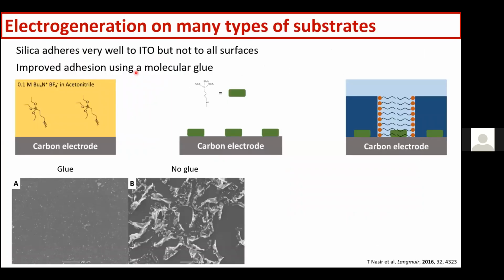So we can electrogenerate these on many conductive and semiconducting substrates. It works very well on ITO, indium tin oxide, or FTO, fluorine tin oxide, because of the presence of oxygen groups on the surface that can form covalent bonds with the silica film. But sometimes we need to help the adhesion using a molecular glue. So in this case, we were first electrografting aminopropyltriethoxysilane, to form a covalent bond between the nitrogen atom and the carbon electrode. And then we had silanol groups that were available to form bonds with the growth of the silica.